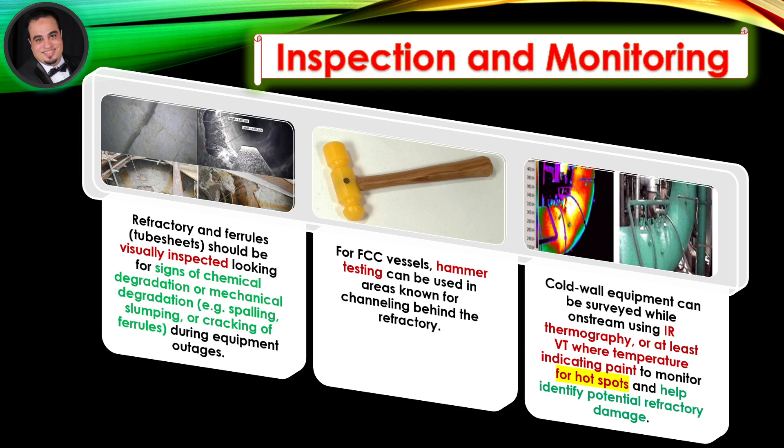Cold wall equipment can be surveyed while on-stream using IR thermography, or at least visual inspection with temperature-indicating paint, to monitor for hot spots and help identify potential refractory damage.